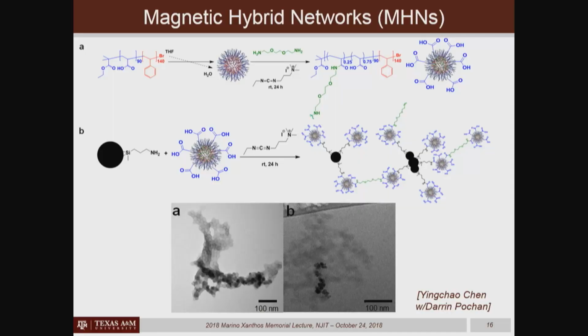And she figured this out initially by looking at transmission electron microscopy images. On the left side here, this TEM image shows us down in this region that there's this heterogeneity of contrast. There are some dark regions of inorganic particles not allowing transmission of the electrons, and there's some lighter regions of the organic particles. But up in this region, you see there are organic particles clustered together without any inorganic particles linking them together. And so we weren't sure whether that was just a drying effect on prepping the sample on the TEM grid.